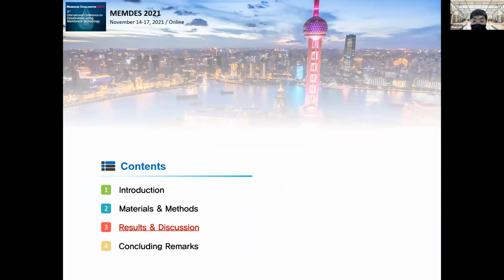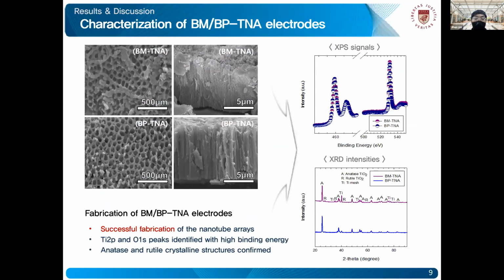Now I'll briefly go over the results and discussion part of our research. After the fabrication of our novel BM and BP TNA electrodes, we analyzed the electrodes through SEM, XPS, and XRD analysis. The SEM imagery shown on the left side shows the successful fabrication of the nanotube arrays on the Ti mesh and Ti plate electrodes. Through the XPS analysis, we identified the Ti 2p and O 1s peaks with high binding energy from the annealing. Also, the XRD intensities show that anatase and rutile crystalline structures were confirmed on the TNA electrodes.